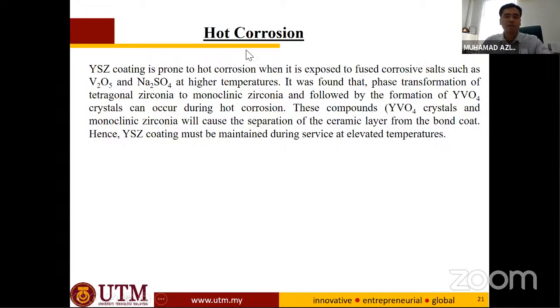Right, so we also have hot corrosion. This is another issue in the ceramic coating. Why is that? It's prone to hot corrosion. So why do we want to have the hot corrosion test here? Because you need to remember, if you're talking about aviation, aircraft, they fly at high altitude. So the moisture and air also contain corrosive salts, for example vanadium pentoxide or sodium sulfate. At this high temperature, you're talking about 1200 degrees C for the gas turbine, isn't it? So you're talking about high temperature oxidation.